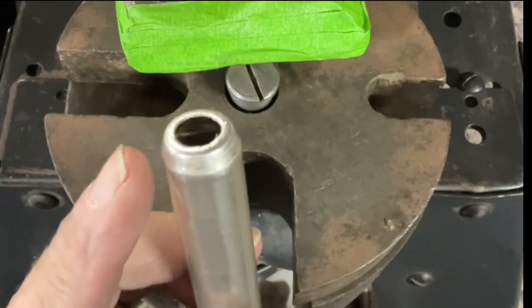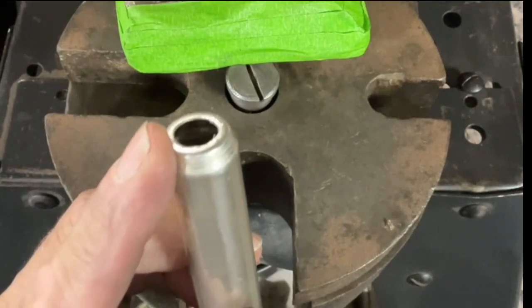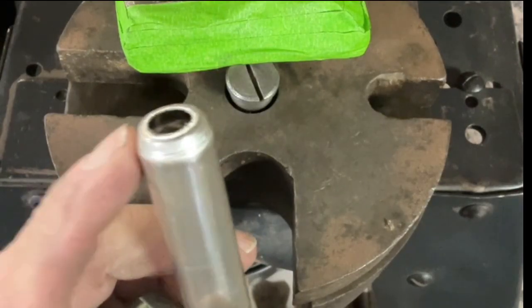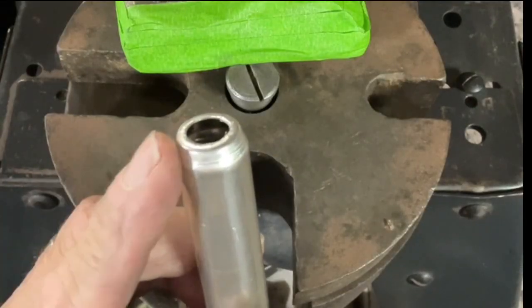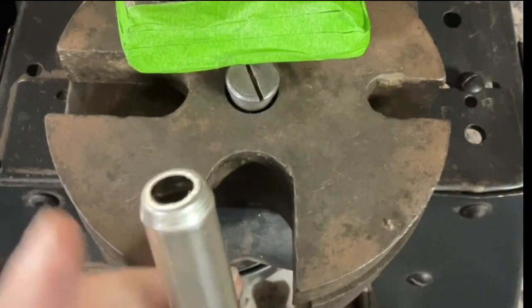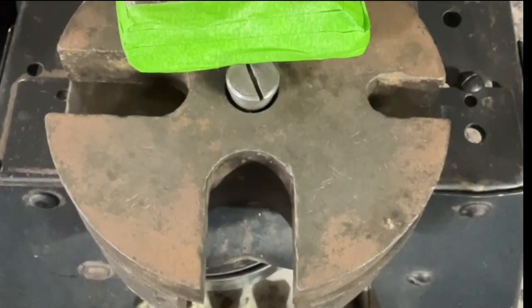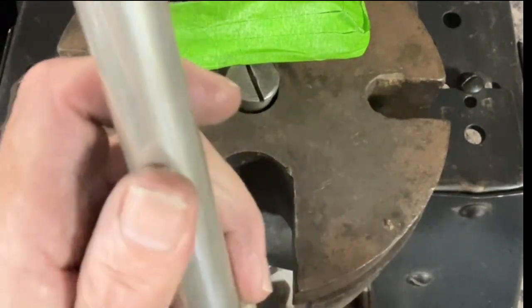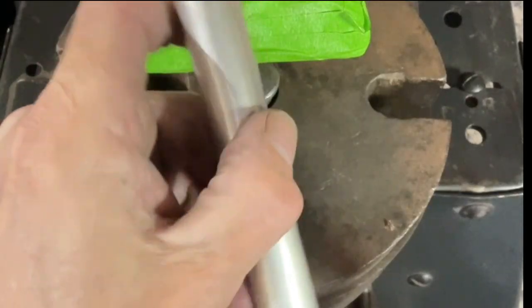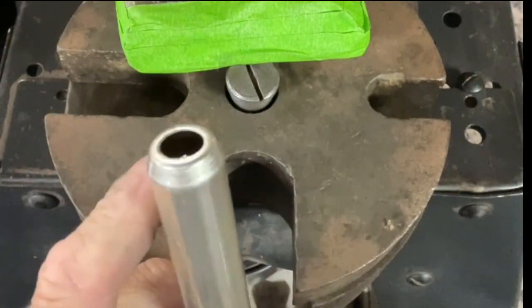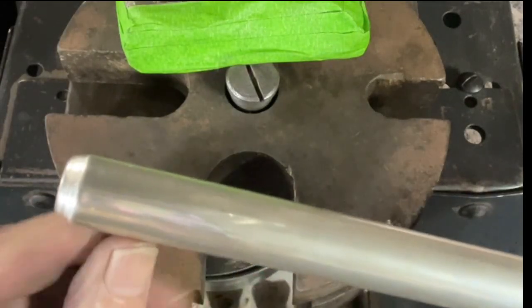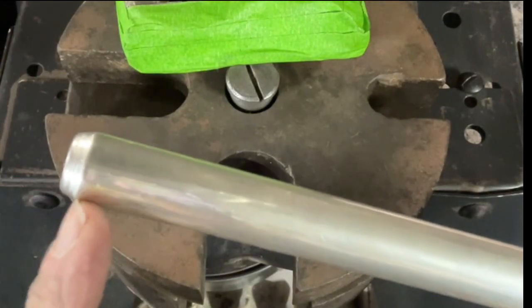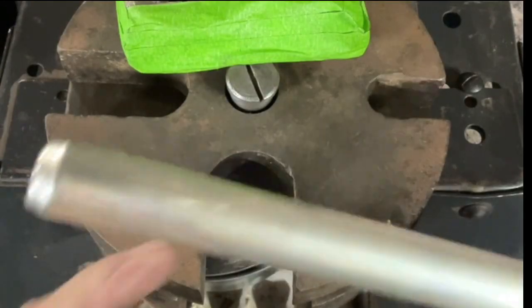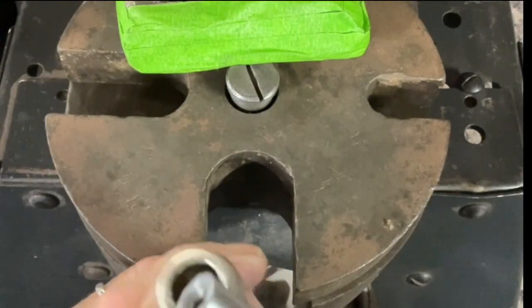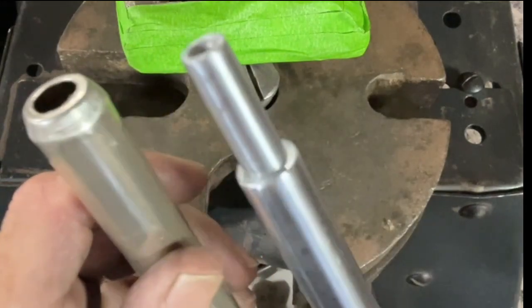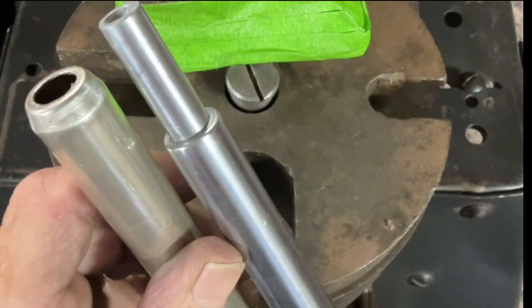I used to do this by quench annealing the tip and using this method, also quench annealing it and putting it in a lathe and using a power burnisher. But I've settled on this method. I use a half-hard tubing, and if you do this too quickly, you're going to get accordioning here or at the base. Now, since I have a good corner here, I'm going to be able to take my drawing mandrel